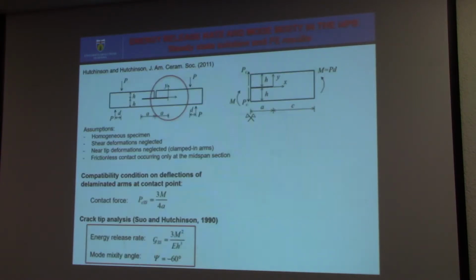And Suo and Hutchinson in 2011 obtained an analytical solution for the energy release rate and the mode mixity angle. And that solution was obtained based on a number of simplifying assumptions. They assumed the specimen to be homogeneous. They neglected shear deformation. They neglected near-tip deformation, so they assumed the delaminated arms to be clamped at the crack tip cross-section. And they also assumed frictionless contact, so they neglected friction in the solution.